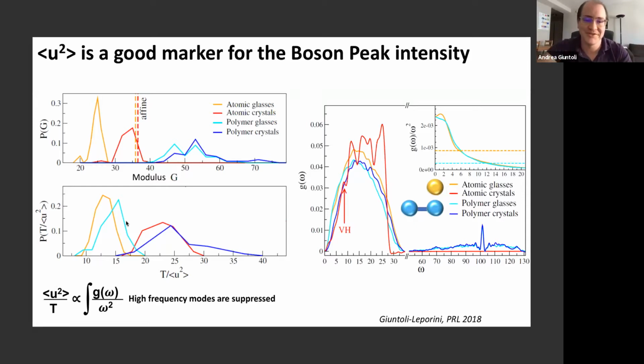Why the Debye-Waller factor? In the harmonic approximation, it is not black magic. The idea is that the Debye-Waller factor in harmonic approximation is just the integral over all the density of states divided by omega squared, which means that the high frequency modes of the bonds were suppressed. And so we see this nice coupling here.